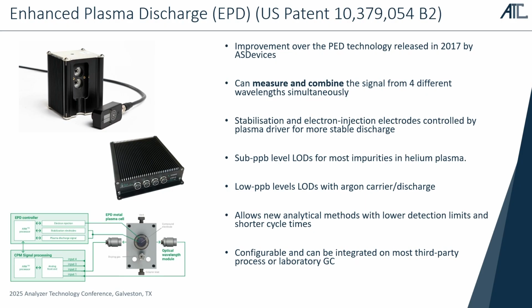But due to some of the drawbacks of the PED technology, in 2017, AS Devices introduced the enhanced plasma discharge, or EPD, which can now measure and combine up to 4 different wavelengths at the same time, which is going to allow a new measurement method that I'm going to present in a few minutes. Also, we introduced some electron injection and stabilization electrodes to improve the signal-to-noise ratio and therefore improve the limits of detection. So now we can reach sub-ppb limits of detection using helium as the plasma discharge gas, but we can still also reach low ppb level limits of detection using argon as a carrier gas. And also something that might be interesting for you is that this technology can be integrated on almost any third-party process or laboratory GC on the market.